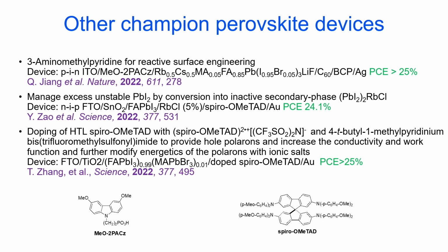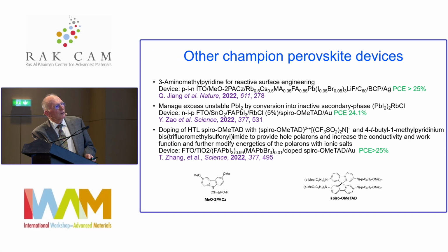Now, I've summarized some other results here because going through it all gets a bit tedious, but there are some tricks to be played. Surface engineering, using aminomethylpyridine, and all the structures are there. I won't go through them. 25%. This is an interesting one because lead iodide is one of the outcomes of instability of the lead alkyl ammonium or other lead perovskites. And this trick was to convert it into an inactive secondary phase with rubidium. And that device showed a nice efficiency, 24.1.